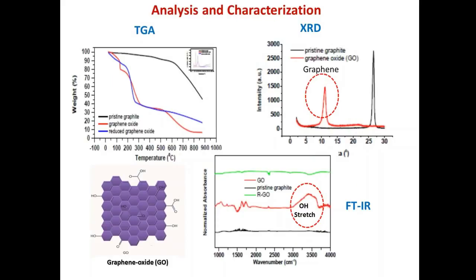You can also follow this type of dispersion and reduction by methods such as thermogravimetric analysis, infrared spectroscopy, and XRD. Thermogravimetric analysis tells you how much oxygen is incorporated on the graphene. The XRD gives us a picture of the degree of exfoliation and periodic stacking. The FTIR gives us the functional group present on the graphene oxide, which is absent with the pristine material or a graphene derivative.